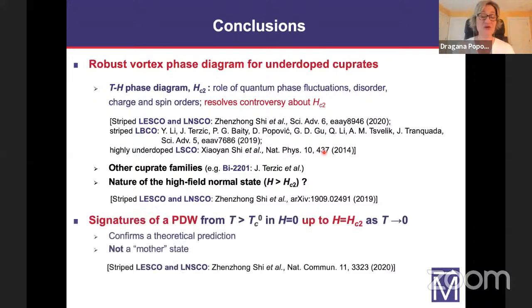I also showed you results that confirm a theoretical prediction. So it seems that these materials do really host a paired density wave. However, even though this does not seem to be a so-called mother state or responsible for the pseudogap in these materials, it is obviously important also to probe other cuprates in the high field regime, beyond the melting field of the vortex solid. And I know there have been some such efforts so far, but this work is still ongoing.